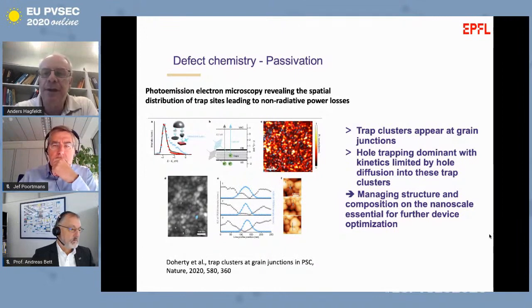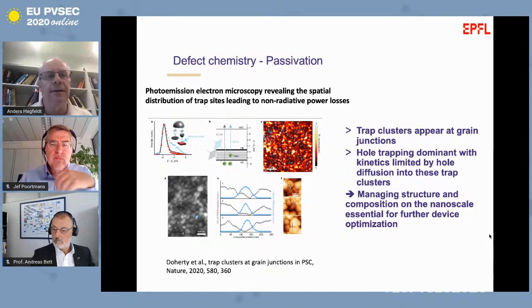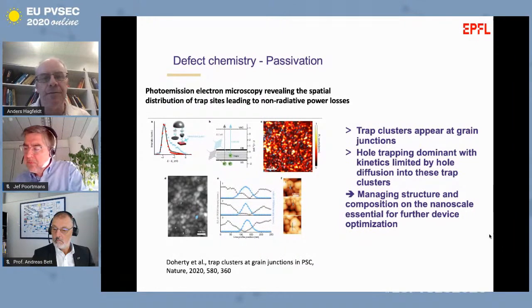There's a hole trapping event which goes quickly kinetically to these trap clusters. So it's not a homogeneous non-radiative trap distribution. It's localized in grains, and that's where we have to find strategies to passivate these recombination centers.